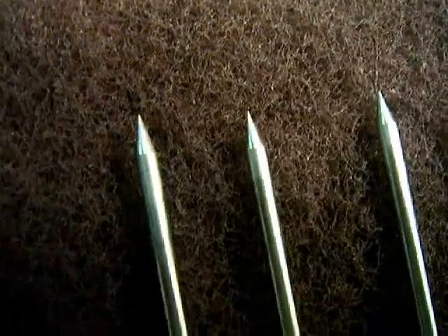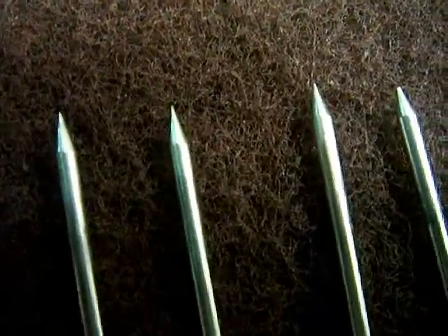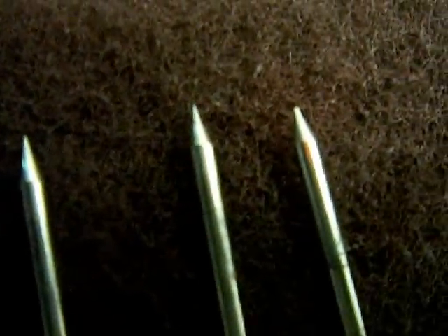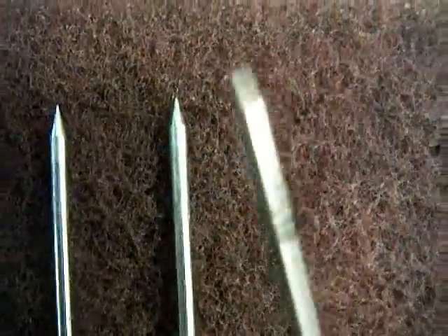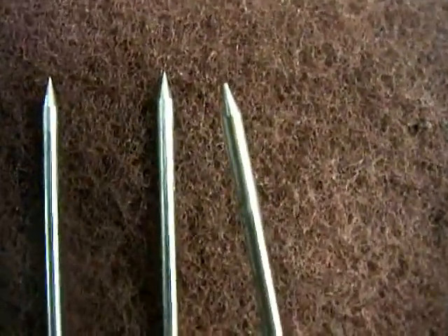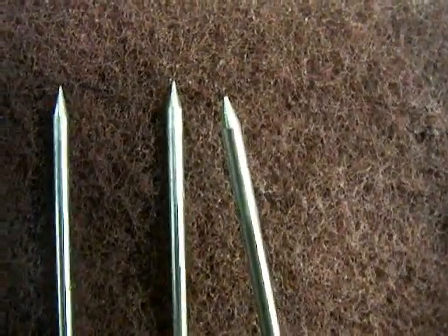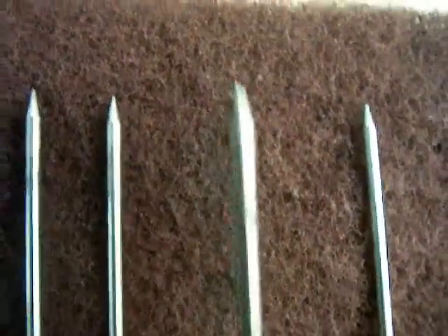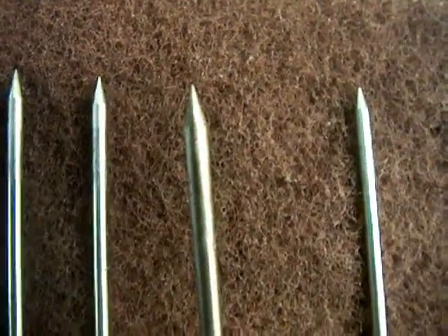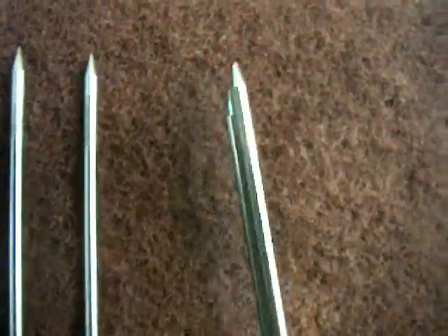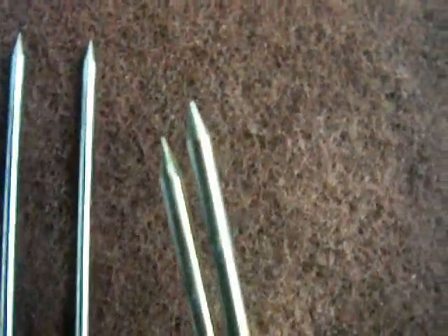As you can see, there's not a whole lot of difference. Most of them maintain their sharp tip. What was kind of surprising was the 2% thoriated melted that sharp tip a little bit more than the rest of them did. So even the ceriated and the 1.5 lanthanated held up a little bit better than the thoriated, and the 2% lanthanated again just fine. The first 3 pretty much no difference. The thoriated actually eroded a little bit, melted the tip a little bit at 200 amps with a shock of 200 amp blast.